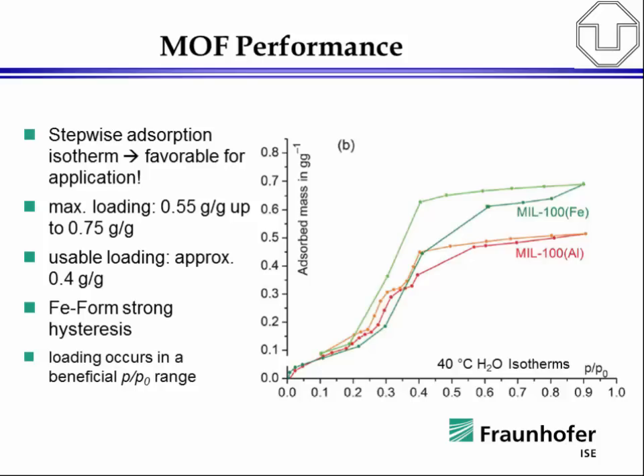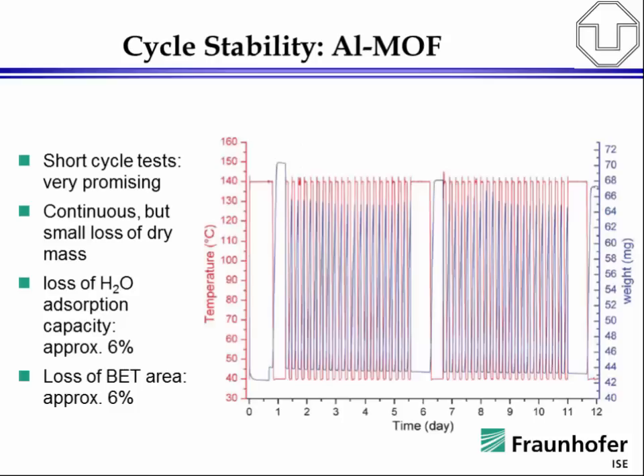And essentially for the heat pump, it is necessary because you want to pump between two relative pressures, two humidity levels, like a high humidity level and a low humidity level, so that you don't need too much energy to desorb the water again. So for this sort of stepwise water adsorption isotherm is extremely beneficial. Of course, in this type of application, durability is the key,